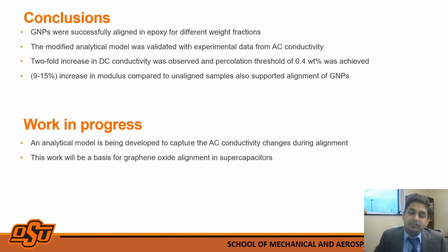To conclude, we successfully aligned graphene nanoplatelets in epoxy, and an in situ characterization technique was established which could quantify the alignment process. We also achieved a twofold increase in DC conductivity and a percolation threshold of 0.4 weight%. The future work is to capture the AC conductivity by an analytical model and extend this to graphene oxide for application of supercapacitors.